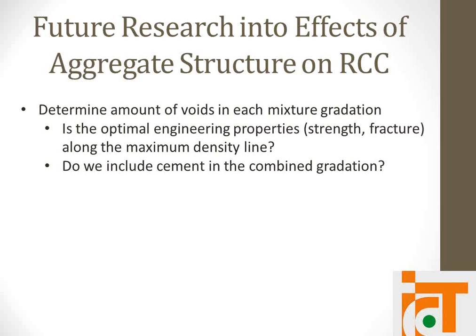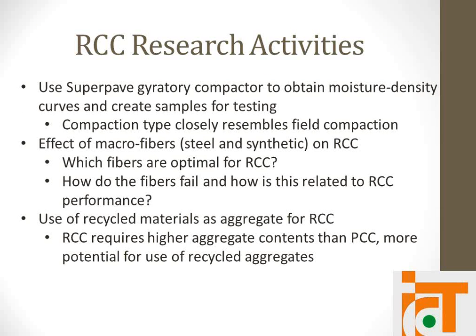Some of the things we want to look at further as to the effects of aggregate structure on RCC are: are strength and fracture optimal along the max density line, or is there an optimal gradation that yields the highest properties, and how do fines contents affect this, and should we include cement in the gradation as well and optimize the gradation while including cement. And future research for RCC in general is we want to look at using the superpave gyratory compactor, and the thought behind that is to correlate better with field cores and companion cylinders. The gyratory compactor with its shearing action will more closely resemble the in-field compaction.